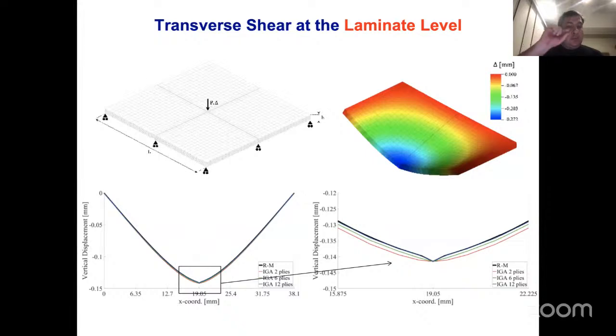And so with each definition, the layers get thinner and thinner and thinner, but their sum total is the same. And then these layers are connected with the cohesive interfaces, where the cohesive stiffness parameters can be computed to be consistent with the behavior of a solid. In fact, you can directly compute the value of a cohesive stiffness by mimicking a pure shear condition, for example. And so then we take a point load, we put it in the middle of a plate like this, and then you get a deformation like this.